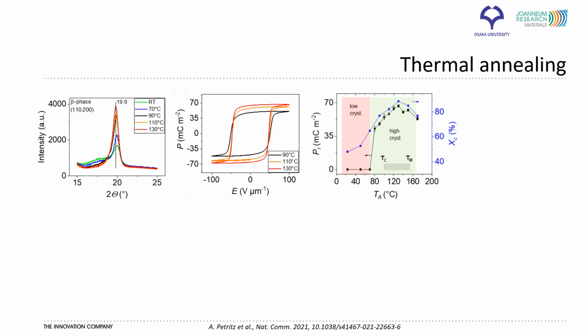For the ultra-flexible sensors, we have performed a very careful investigation of the influence of thermal annealing after sensor fabrication. In XRD measurements, we have observed an increase of the crystallinity parameterized roughly by the height of the 110 reflection peak for annealing temperatures in the range of 70 to 130 degrees. 130 degrees is above the Curie temperature but below the melting point. The increase in crystallinity is accompanied by a proportionate increase in the remanent polarization.